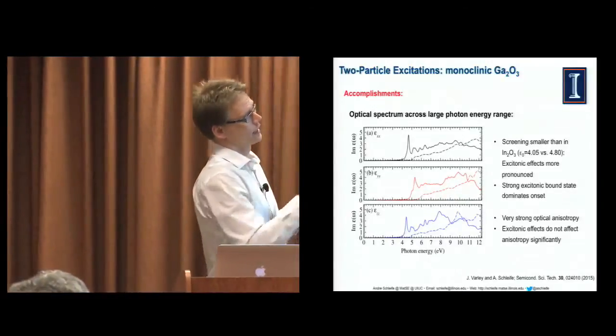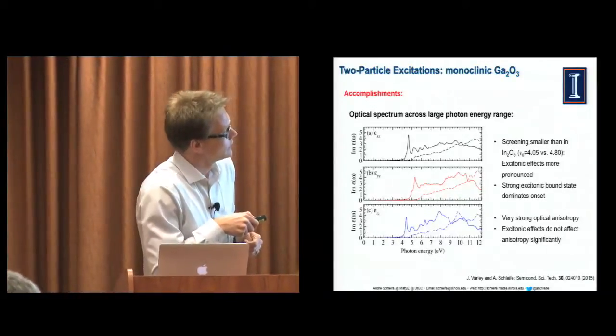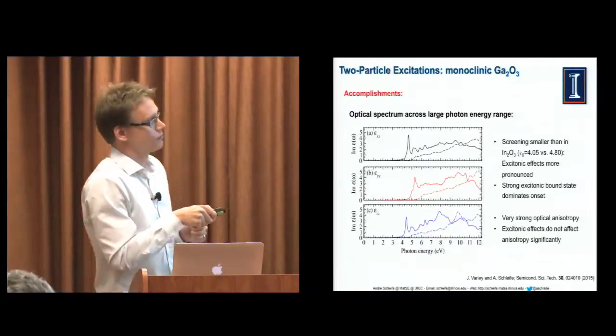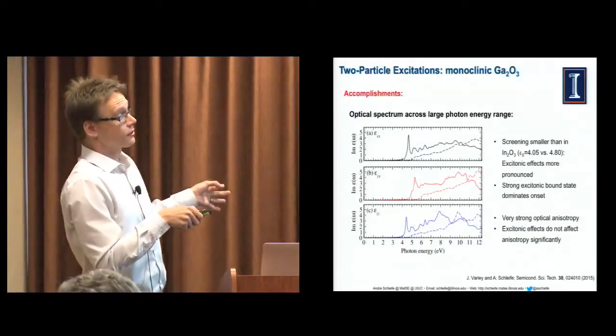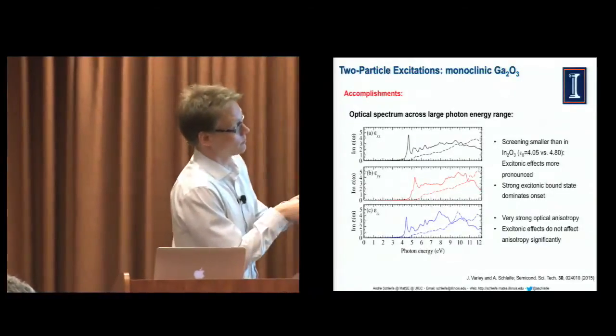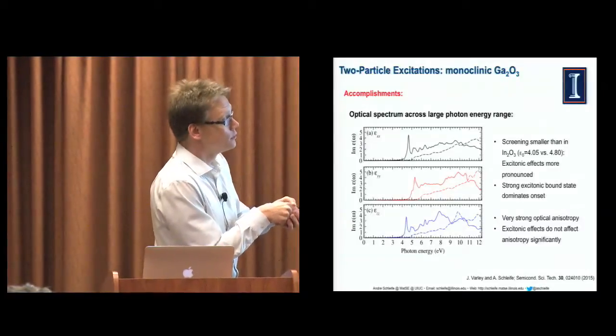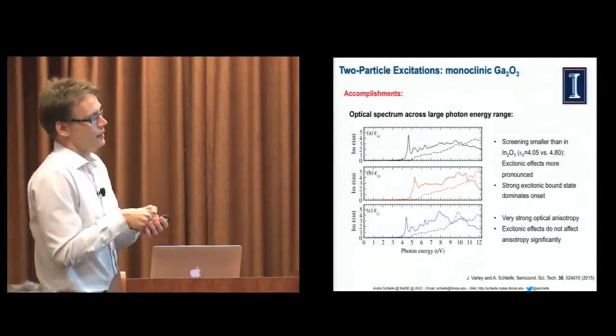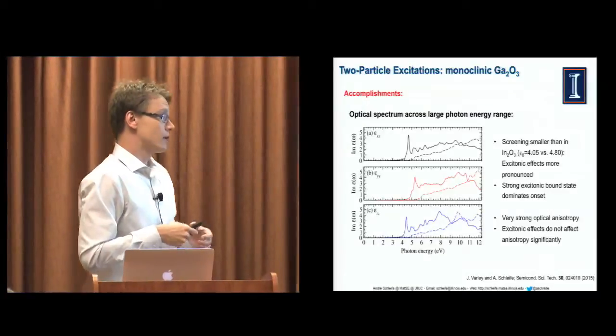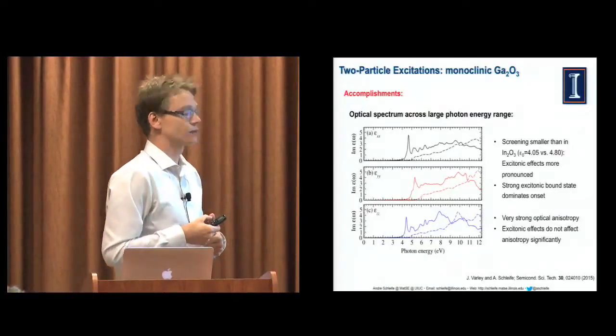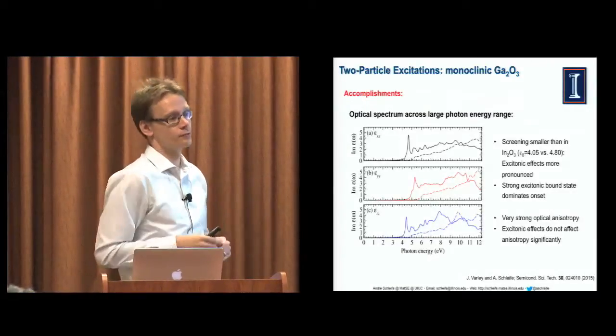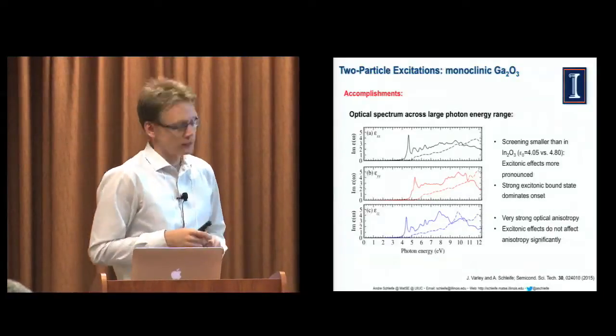That's actually gallium oxide. You can see, again, the dashed lines are DFT and the solid lines are Bethe-Salpeter calculations, and in all cases, right at the absorption onset, you get this huge enhancement of optical absorption. You get this redshift. So in other words, you need this approach to describe an optical spectrum if you want to compare to experiment. Otherwise, you're lost, right?